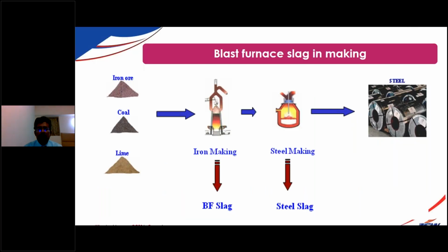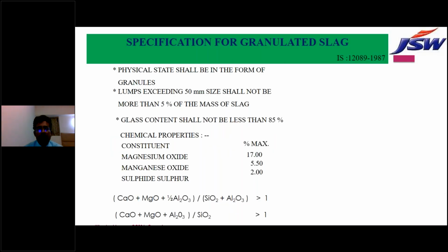So this is the line diagram showing how we feed limestone, coal and iron ore together into the blast furnace. So we get iron making and we get blast furnace slag, that we convert into GGBS, and we also convert into slag sand. Looking at the chemical composition, my dear friends, this has a very good chemical composition. As per the IS code requirement, the glass content should be 85% minimum, but what we are making is more than 95%.